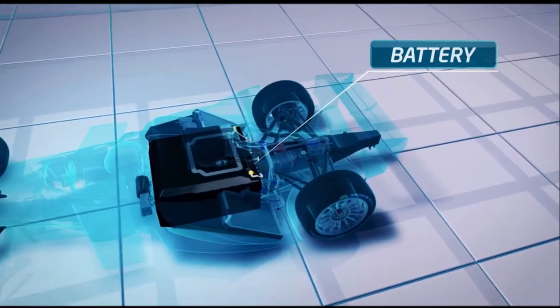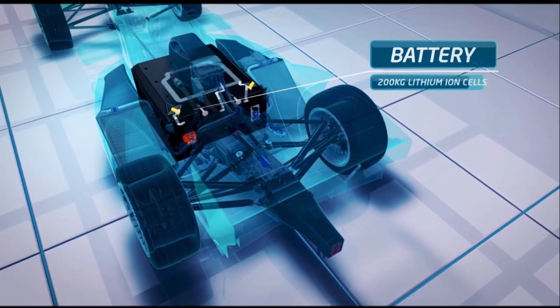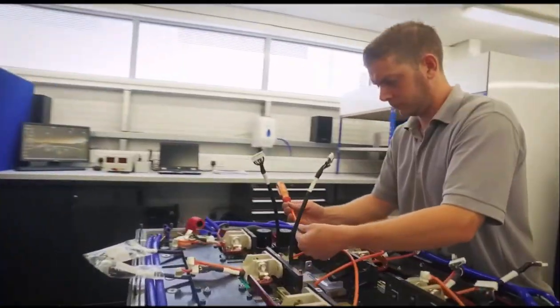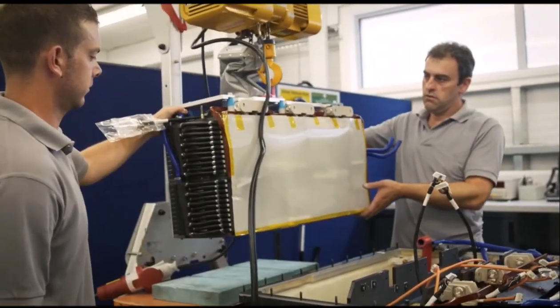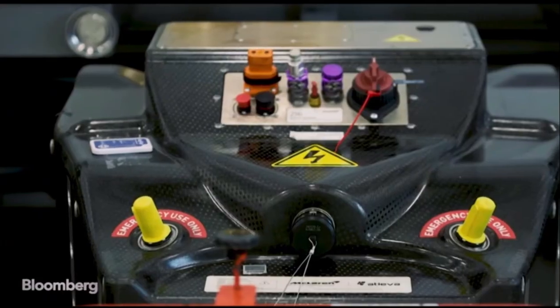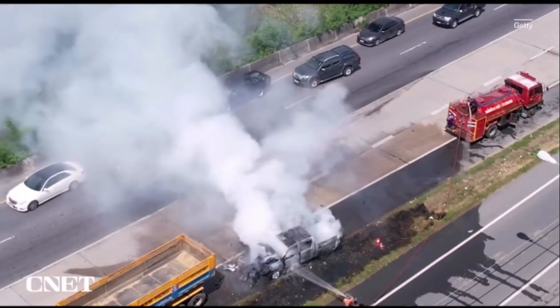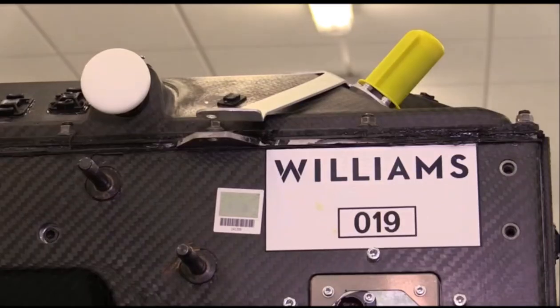What does that mean? Well, Williams themselves have admitted that they are able to provide a fireproof box that their batteries sit in. This carbon-ply material they've manufactured is actually able to withstand the fire of a lithium-ion battery for 10 minutes — enough time for emergency services to retrieve a driver out of the car and begin the flooding process. The batteries designed by Williams have what they call a dousing port on the top, where a tanker or fire engine floods the entire container and seals all that heat inside whilst trying to cool it down.